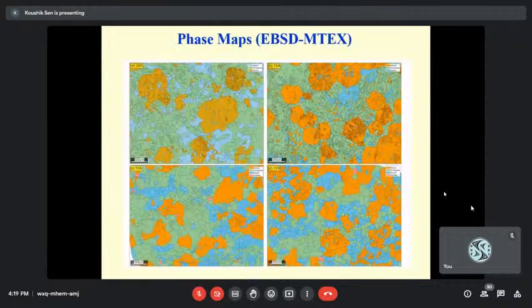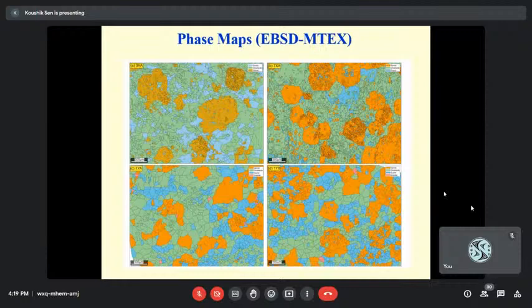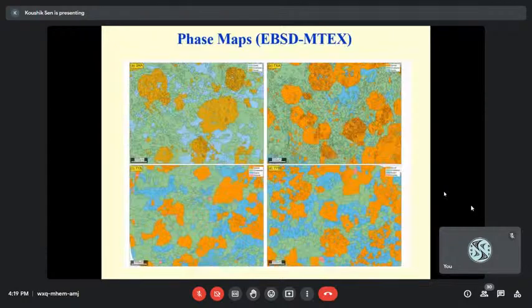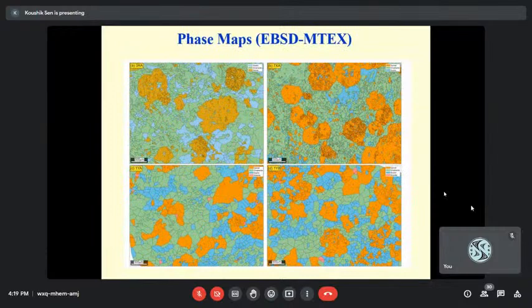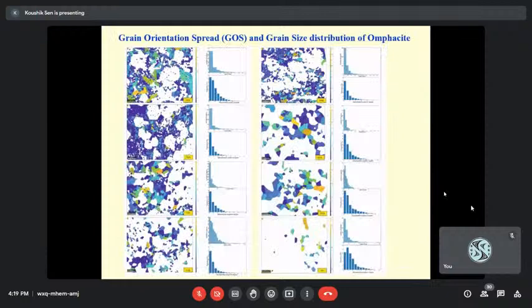Some phase maps by EBSD, you can see the presence of garnet. The orange color minerals are garnet, the blues are quartz, and the green are omphacite. Now before we talk about the lattice preferred orientation or the grain boundary misorientation of the omphacite to understand the deformation mechanism and slip systems, we have to know first how deformed or how much distortion this omphacite really has, and at the same time visually we want to show how the amount of omphacite also decreases from type 1 to type 2. So that is one parameter that is called the grain orientation spread.